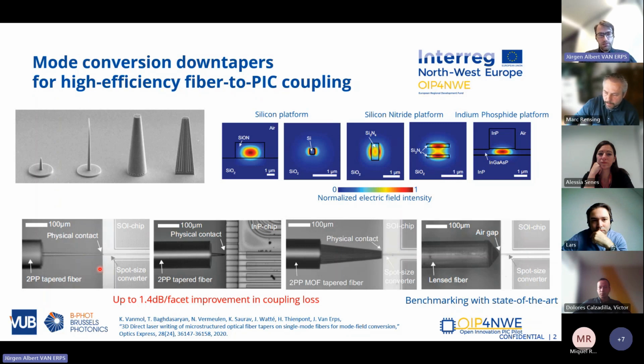We have then been using a 3D nanoprinting process based on two-photon polymerization to print those structures directly on top of optical fibers. So here you see them printed on a plain substrate, and this is the linear down taper on a glass substrate, but we can directly print them on top of the fiber such that we have an excellent alignment of the down taper to the center of the fiber, and then we can couple to the chip with a physical contact.